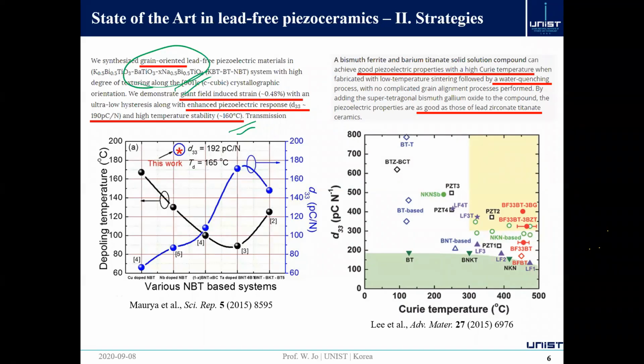In the meantime, we have another good achievement using a completely different technique, called water quenching. When it comes to bismuth ferrite, you know that its spontaneous polarization is so high that it could be a really nice ferroelectric material, but the problem is you cannot get phase pure bulk bismuth ferrite because of the metastable phases between the cubic point and room temperature.